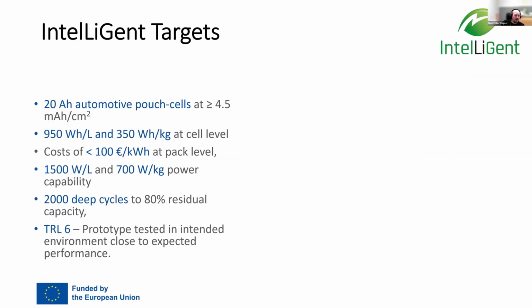The targets that we set ourselves are to make these cells as 20 ampere-hour automotive pouch cells that operate at 4.5 milliamp hours per square centimeter areal loading. By this, we could achieve energy density values of up to 950 watt-hours per liter or 350 watt-hours per kg at cell level, with a price tag of below 100 euros per kilowatt-hour at pack level. Also, we answer the call for power capability of up to 1500 watts per liter or 700 watts per kg. And the cell is supposed to be cyclable for 2000 deep cycles down to 80% residual capacity.